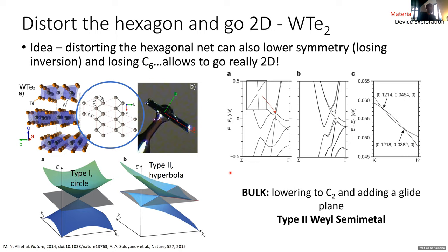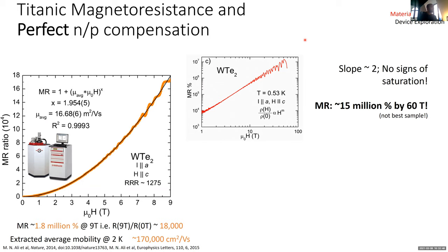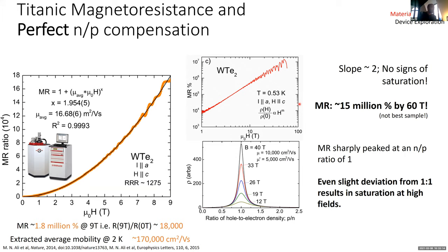But when we started looking at the properties, of course, we found something completely unexpected, which was that the magnetoresistive effect is just enormous, and it shoots pretty much to the moon, actually. There's no signs of saturation up to the highest magnetic fields we were actually able to apply, so 60 Tesla. And it just keeps going. And this had not actually been seen in any known material at the time. And the reason for this lack of saturation, it turns out, is explainable semi-classically. It turns out that if you have a nearly perfect ratio of holes and electrons, you can sit on a pole where the magnetoresistive effect can increase arbitrarily. And if you deviate from that ratio, from nearly perfect, then you end up with saturation like had been seen in basically every other semimetal ever.